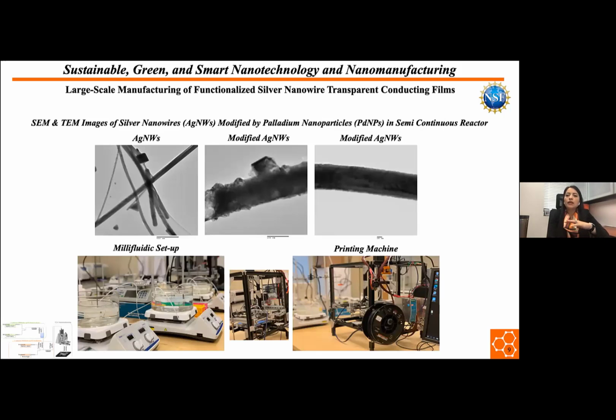In the next step, we have a semi-continuous modification of silver nanowires, which means that when we have silver nanowires produced in the millifluidic system, the outlet of the system is collected in a beaker, cooled down to room temperature, and then we add the palladium precursor or other reagent necessary for the galvanic replacement reaction, by which we modify the surface of silver nanowires using palladium nanoparticles. This is the reason we call that semi-continuous modification, because silver nanowire production is continuous, and in the outlet we have the silver nanowires in ethylene glycol, not water, and then we add the aqueous solution of the palladium reagent or other reagent that we need for the modification.